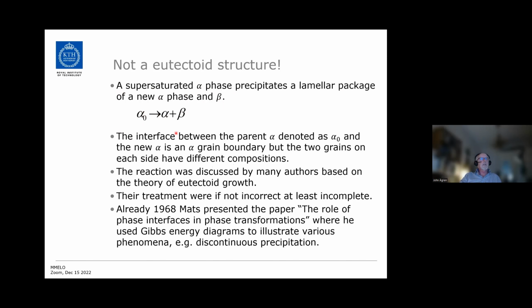Now this interface between alpha 0 and alpha is just an ordinary grain boundary, but there is a difference in composition between the two sides of the grain boundary. And this reaction was discussed by many authors, and one used incorrectly the theory of eutectoid growth because the pictures look like eutectoids. So the theory was, if not incorrect, at least incomplete.